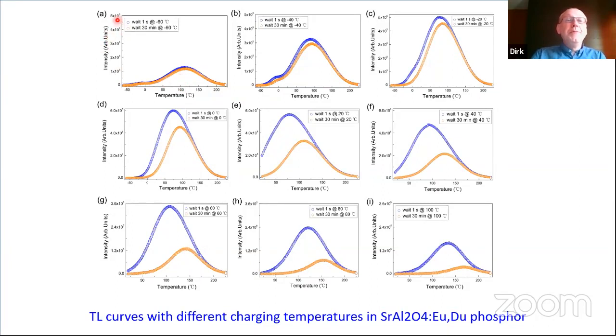Now, if we don't immediately make this thermoluminescence measurement, but we wait for 30 minutes, so we observe a fading time of 30 minutes, then we almost get exactly the same thermoluminescence measurement, which means that at minus 60 degrees, during these 30 minutes waiting time, no light is emitted, because the area under this curve gives an idea of how much light is emitted upon heating the material. But waiting does not make any difference. So at minus 60 degrees, we don't have any light emission.